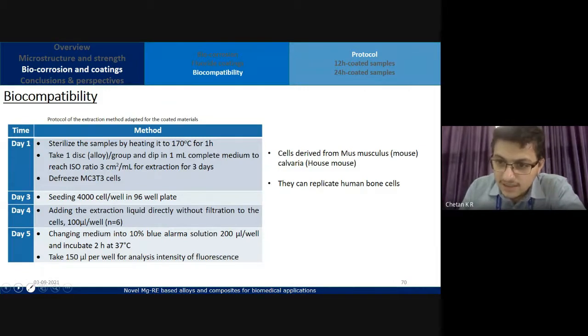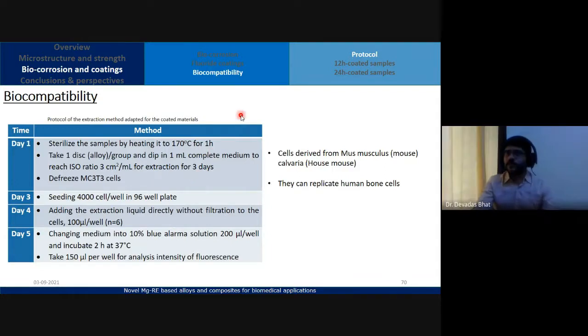Is coating material having any influence on biocompatibility? Yeah, so coating has definitely increased the biocompatibility. Like I said, the cell adhesion and cell proliferation increase with respect to coating. However, we have performed these biocompatibility tests only on the coated samples, because that was our goal. So we haven't really done biocompatibility tests on the uncoated samples. But the coated samples are definitely exhibiting better biocompatibility results because the cell adhesion is increased because of the coating.